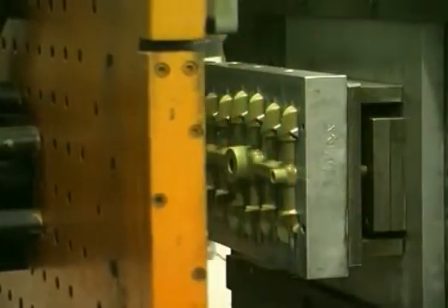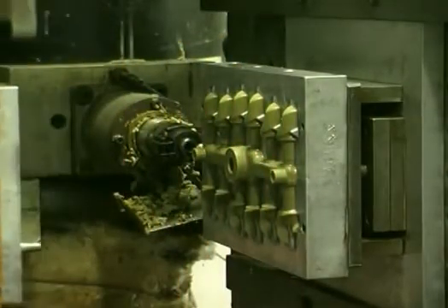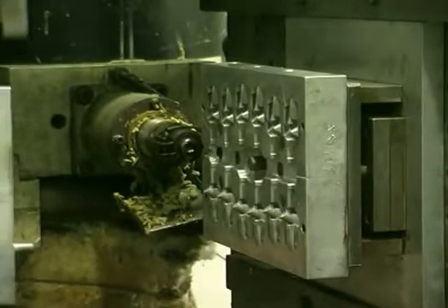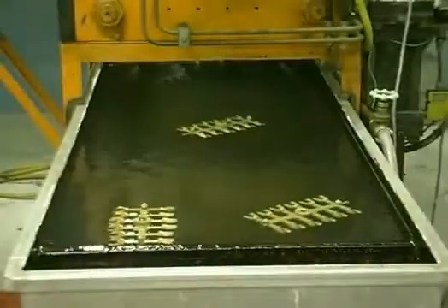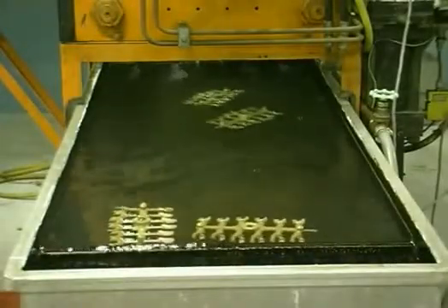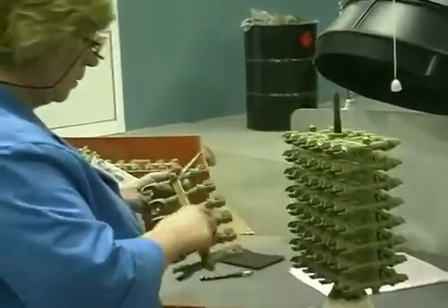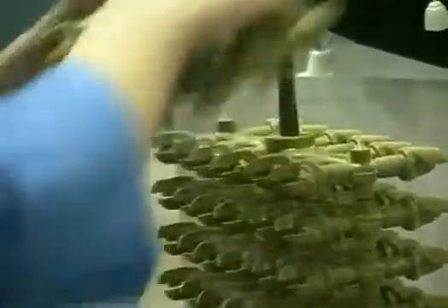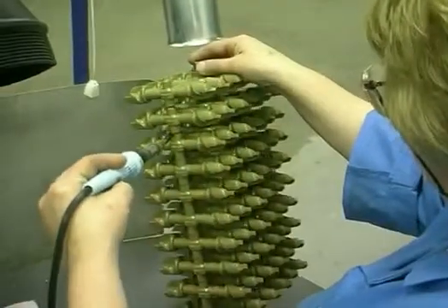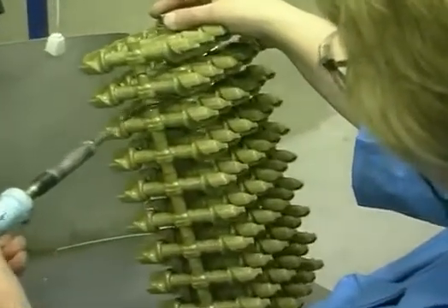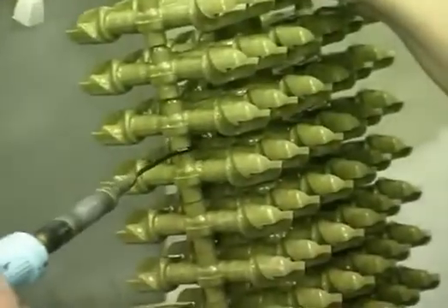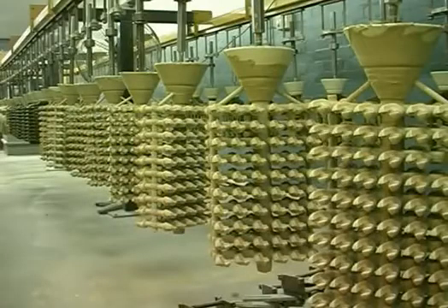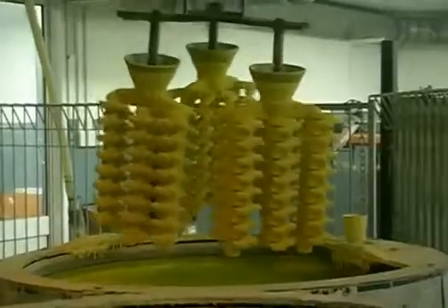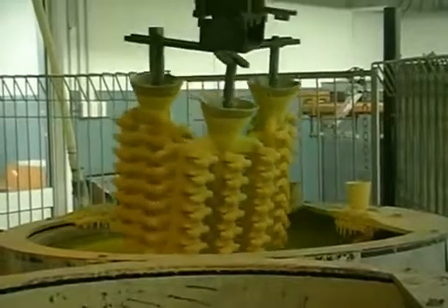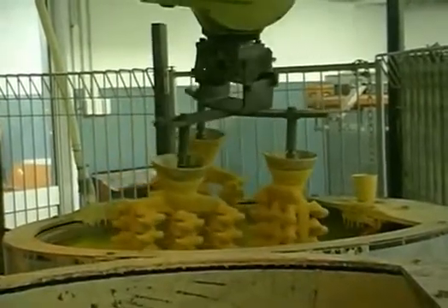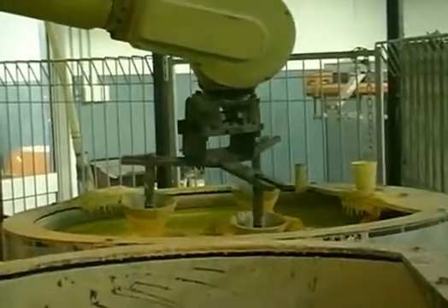These cutter bodies are required in large numbers, and so the wax injection process is automated. The waxes are ejected, the die closes and the cycle recommences. The sets of waxes are carefully checked and trimmed and then assembled on a tree. The segments are welded together, thus forming a runner system. The waxes are first coated with a very fine investment to give good surface detail. It is subsequently built up with 10 layers of zircon sand using a silica binder. The investment process is amenable to automation.